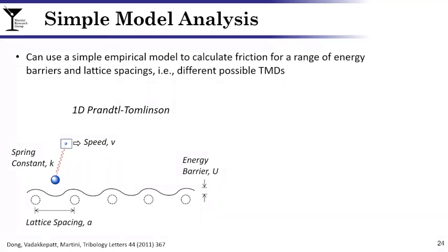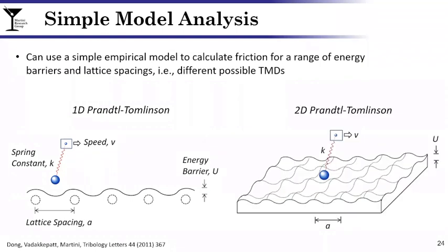Recall that our tip didn't move along a straight line, so we extended this to a two-dimensional Prandtl-Tomlinson model. It's basically the same as the one-dimensional, except the sinusoidal profile goes in both directions. And again, we're capturing the height of the barrier with U and the lattice spacing with A. And just a quick note that these were done using MATLAB codes that are available in the supplemental material of the reference shown on this slide in case you want to repeat the experiment.